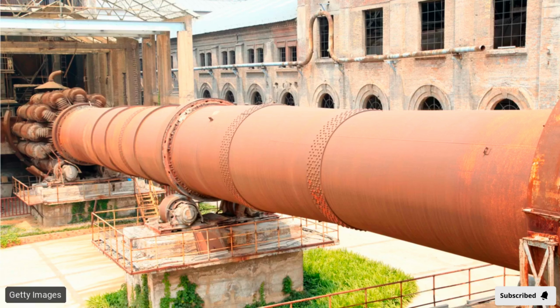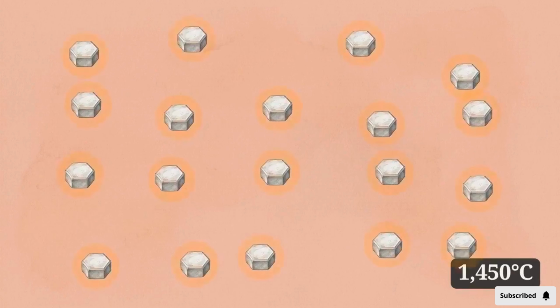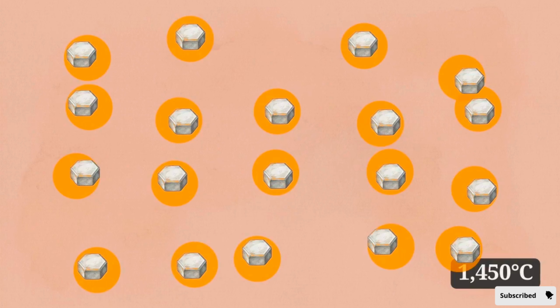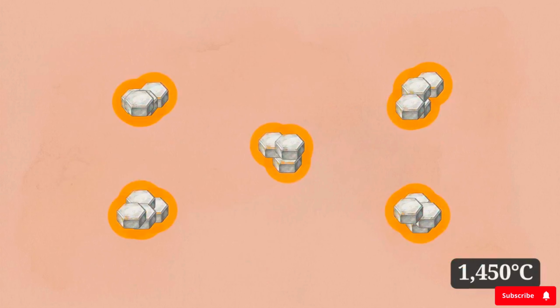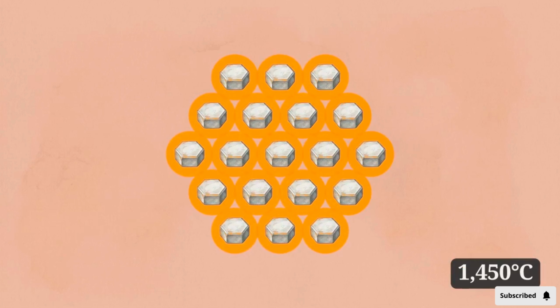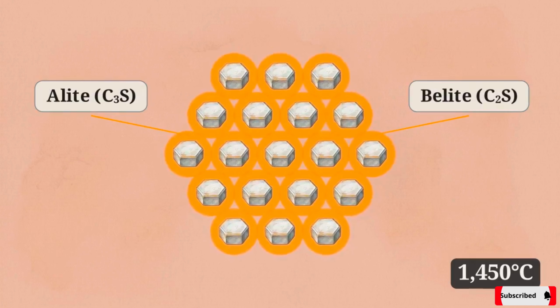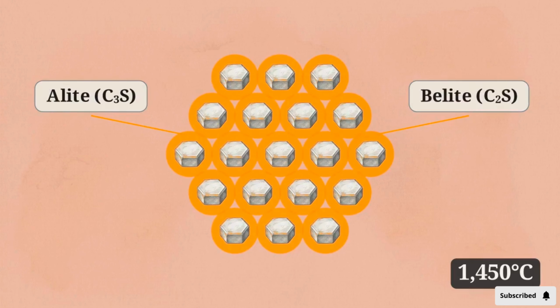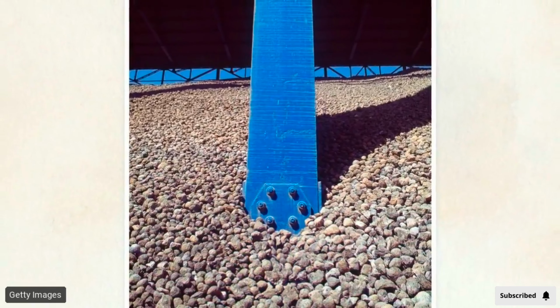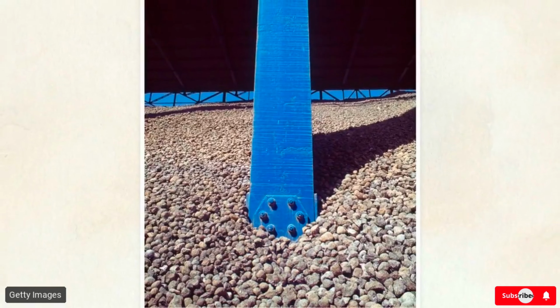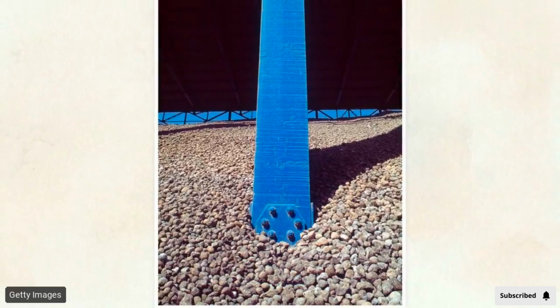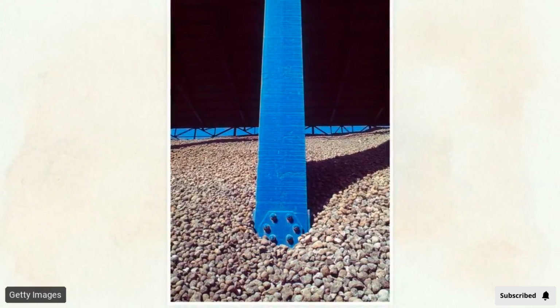The lime now enters the rotary kiln. This is a massive, rotating cylindrical furnace where the material is heated to 1,450 degrees Celsius. Inside, a process called sintering begins. The materials do not melt into a liquid. Instead, their chemical bonds break and fuse together to form new calcium silicates, known as alite and belite. The immediate output of this furnace is clinker. It emerges as hot, rounded nodules that serve as the essential intermediary for all modern cement.